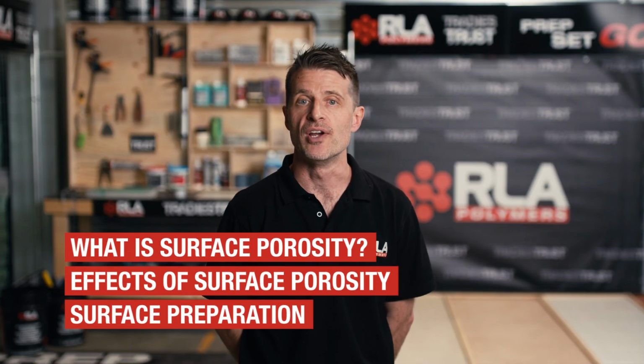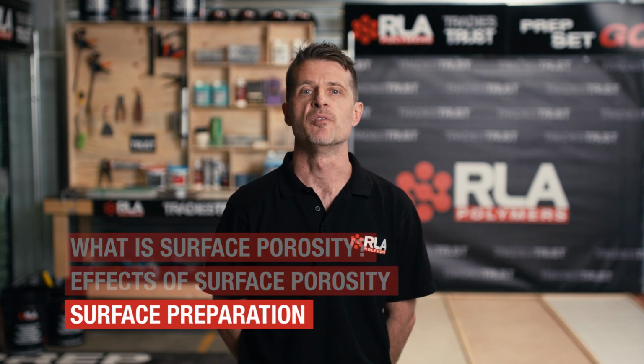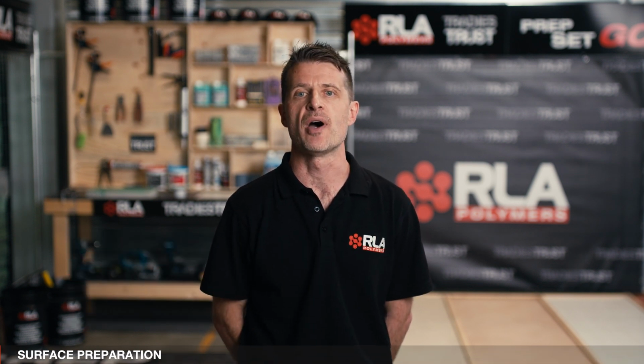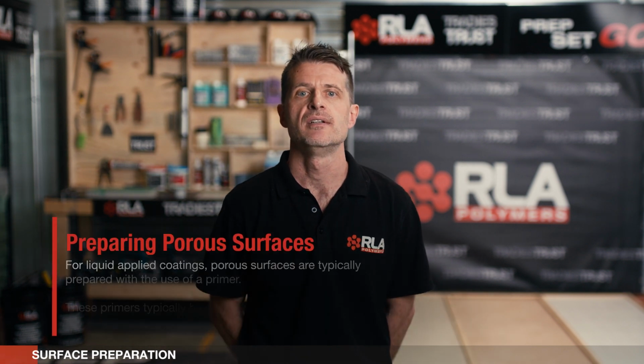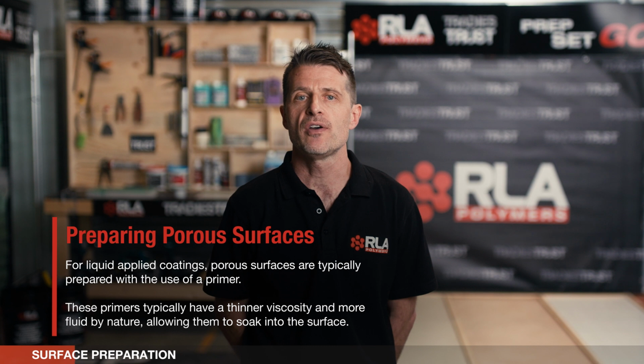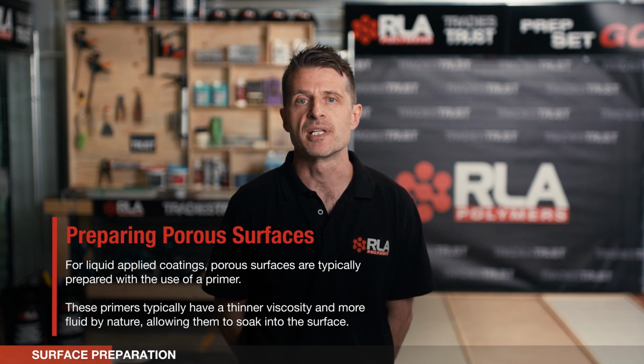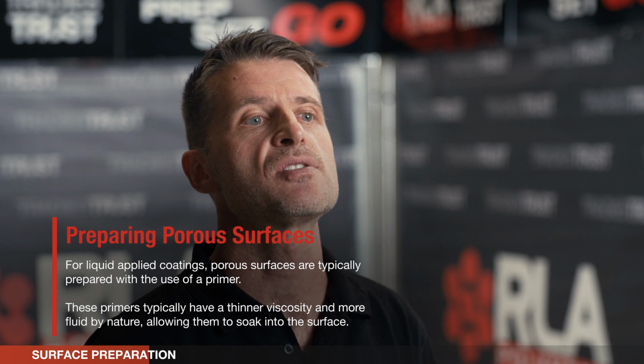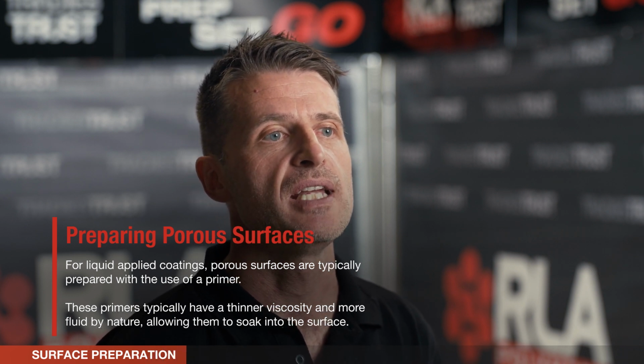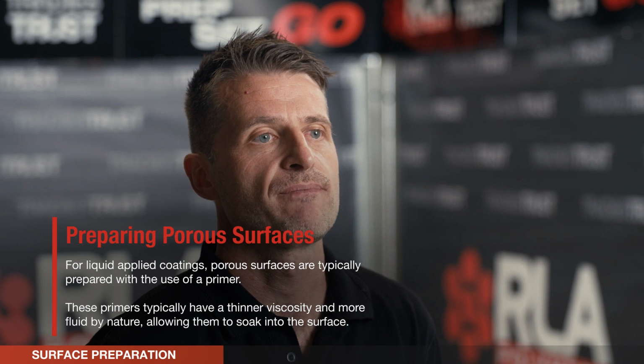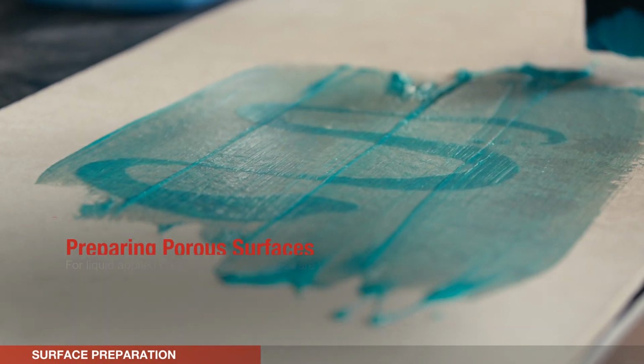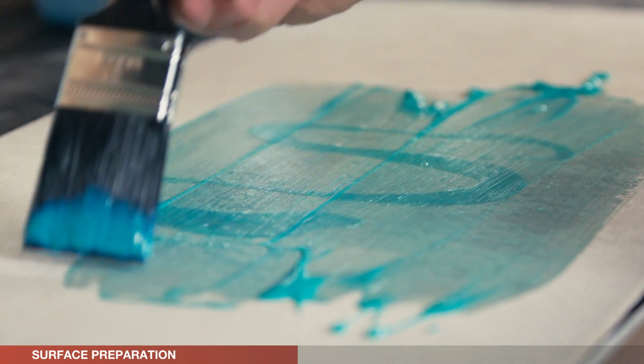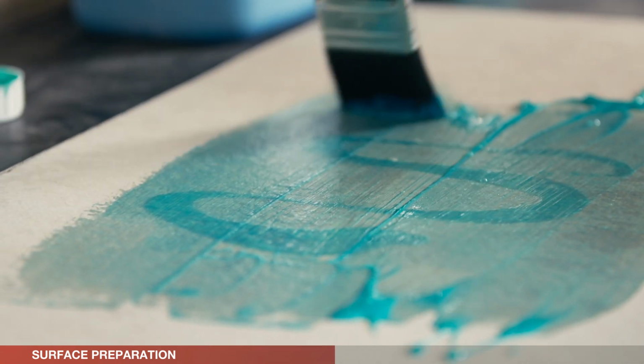Now, surface preparation. As mentioned earlier, the relative preparation required for porous and non-porous surfaces is determined by the manufacturer of the system to be applied. Over porous surfaces, for liquid coatings and waterproof membranes, a primer would typically be required. The primer will soak into the surface and displace the trapped air, in turn reducing the likelihood of pinholing. The primer may also help regulate drying by preventing the rapid absorption and drawing down of moisture from the coating or adhesive. The primer can also help improve coverage by preventing the overabsorption of moisture into that surface.